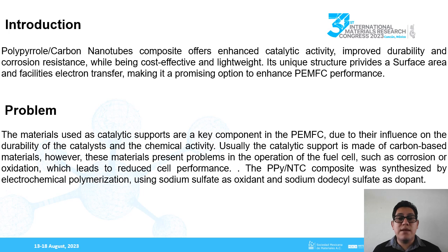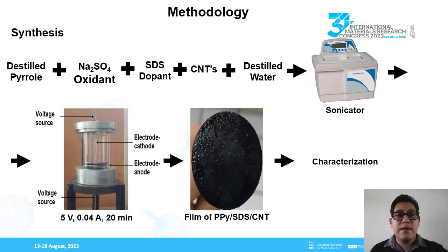It was synthesized by electrochemical polymerization using sodium sulfate as an oxidant and sodium dodecyl sulfate as a dopant. In the methodology, we use distilled pyrrole, oxidant, dopant, carbon nanotubes, and distilled water for preparing a solution, which is taken to a sonicator for its homogeneity. Then, using the electrochemical reactor, the solution is deposited, applying a voltage of 5 volts with an amperage of 0.04 ampere for 20 minutes. The resulting film is weighed, dried, and characterized.